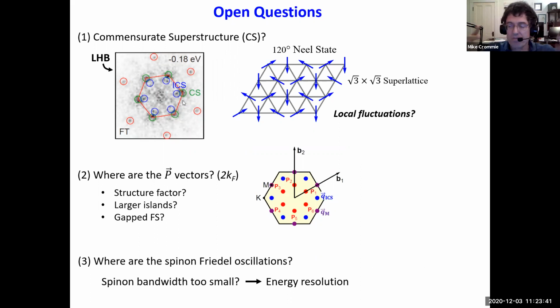And the reason I brushed them under the rug is because the quantum spin liquid cannot explain them. You cannot get those periodicities from a quantum spin liquid. However, a 120-degree Néel state gives you precisely those periodicities. And so we think that what's happening is that we have local fluctuations that can sometimes give us that periodicity. In fact, they do appear as patches on the surface. And so that's what we think that is.